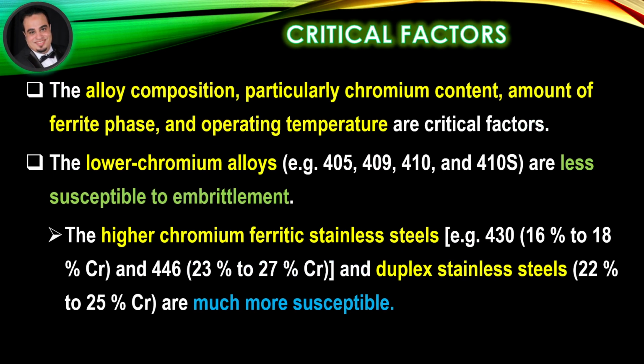Critical factors. The alloy composition, particularly chromium content, amount of ferrite phase, and operating temperature are critical factors. The lower chromium alloys such as 405, 409, 410, and 410S are less susceptible to embrittlement. The higher chromium ferritic stainless steels such as 430, 16% to 18% chromium, and 446, 23% to 27% chromium, and duplex stainless steels, 22% to 25% chromium, are much more susceptible.